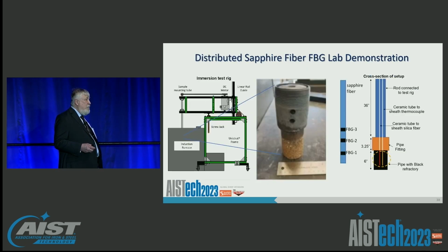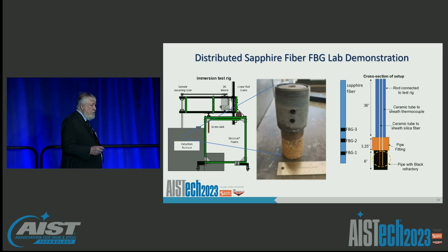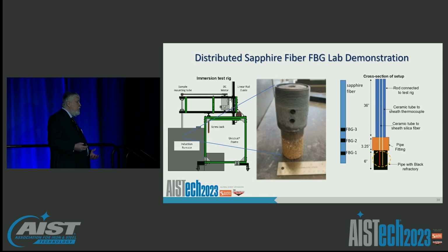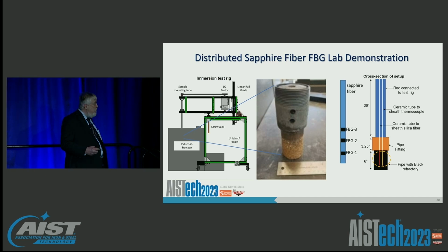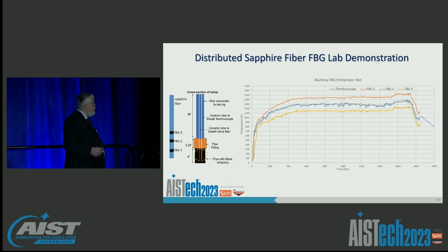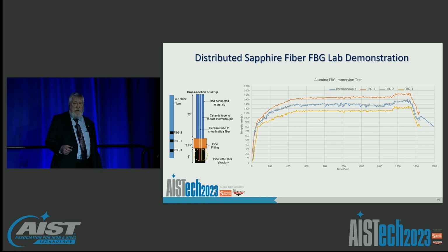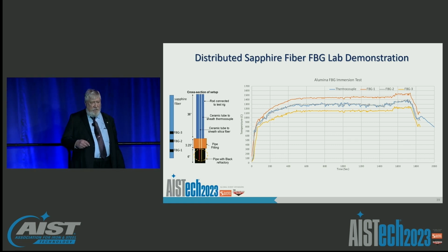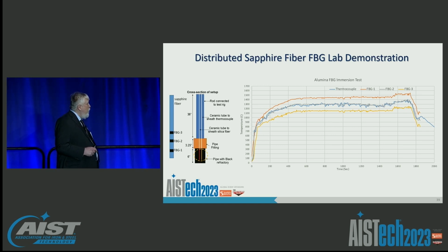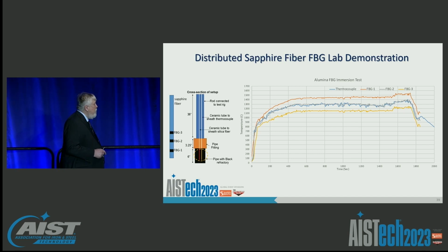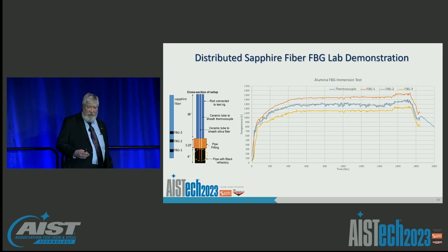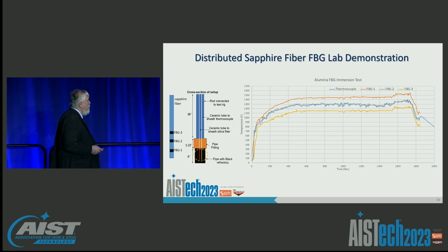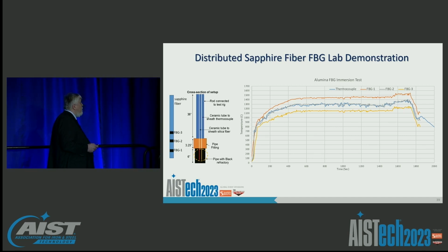So we've actually taken these fibers and put them in commercial alumina carbon and zirconia carbon refractory systems because our interest is actually embedding these directly in the steelmaking process. And so we've demonstrated that we can do measurements quite well with these fiber systems in conventional refractory environments. And actually this shows a sapphire fiber system with 3 Bragg gratings that measure the temperature along the length of immersion of a probe. And the middle one is actually compared to a thermocouple. And you can see, again, the relatively good correspondence of the temperature with the thermocouple position, but we have the added benefit of having multiple measurement points along the length of the fiber. So we can actually measure gradients along that environment.